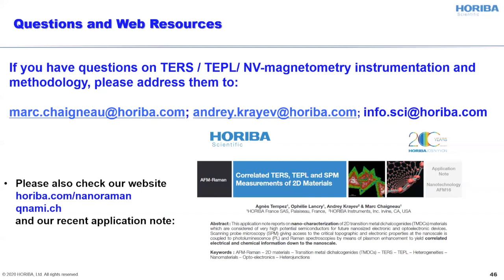All right, thanks. Another one here I see: what is the typical acquisition time for a TERS map, similar to what you've seen for the MoS2, WS2? It depends on the spectral density and how good the tip is. Usually I personally prefer to have fairly dense TERS maps, meaning that I have at least 100 pixels per line. And usually this kind of map takes about 20 to 40 minutes to collect. Okay, moving to the next one.